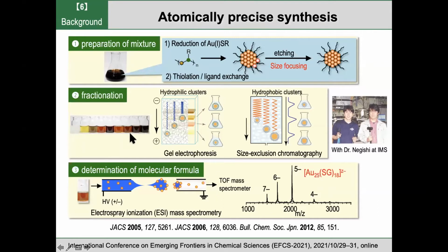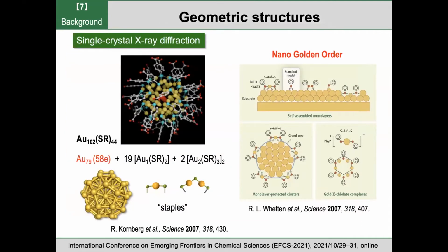And the next question is the structure of the clusters. Professor Kornberg determined the structure of this kind of thiolate-protected cluster by single crystal X-ray diffraction. And he discovered that 79 gold atoms out of 102 form this kind of highly symmetrical core, and other gold atoms are located on the surface, forming sulfur-gold-sulfur small oligomers on the surface, which we call staples. So now we understand the core is protected by these short oligomers in the case of thiol. So we can determine the structure by single crystal XRD if we can crystallize them.